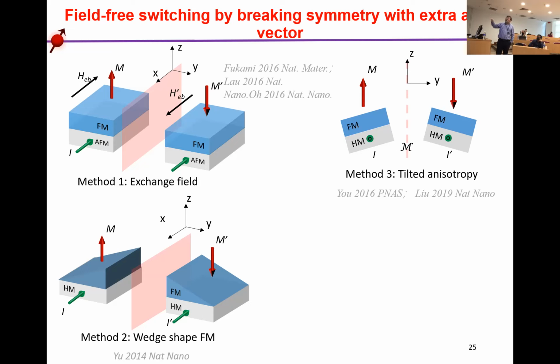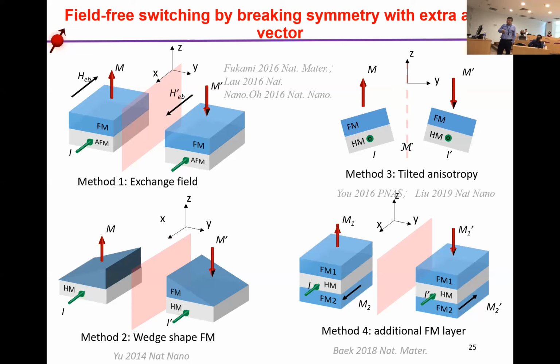Actually, in my group we have done this. I use the sputtering and deposition process to tilt the z-axis away from the perpendicular magnetization to one direction. So this method also can cause deterministic switching of perpendicular magnetization. And the other one, just put a third layer, a soft magnetic material, along one direction. So this behaves like an external magnetic field, breaks the inversion symmetry. So this also can cause deterministic switching.